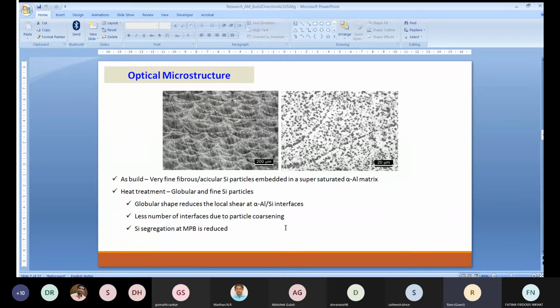Okay, so how this transformation happens in the heat treatment is very simple. When you heat it, the silicon which is segregated at the melt pool boundary will come out, and from the matrix also, both join together and form silicon particles of globular shape. So the advantage of the globular shape is it reduces the local shear at the matrix and silicon particle interfaces. Second is you have a smaller number of interfaces due to the particle coarsening compared to the as-built condition. Third is segregation is significantly removed. Because of these three effects, your ductility has improved.